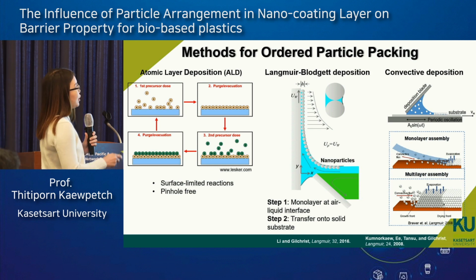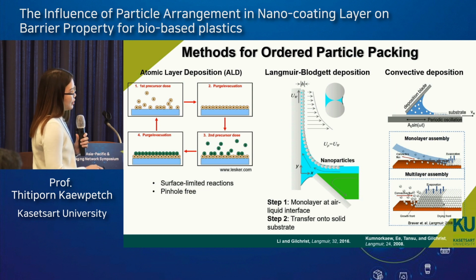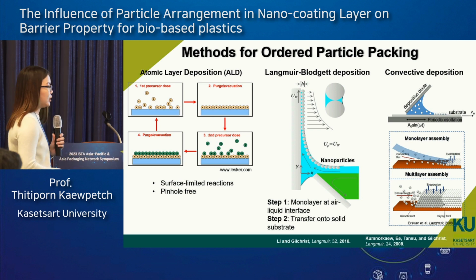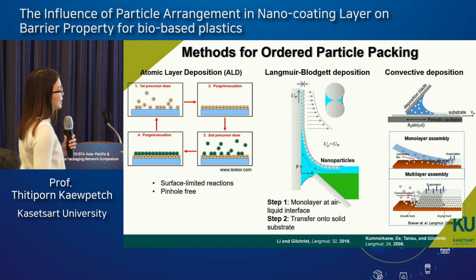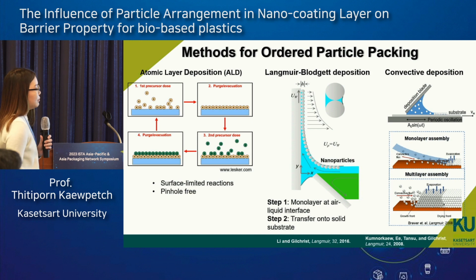Okay, but another one is the solution-based coating. In this case, the particles will be floating on the air-liquid interface and form a monolayer. This monolayer of the particles will be transferred onto the substrate when the substrate is moving.